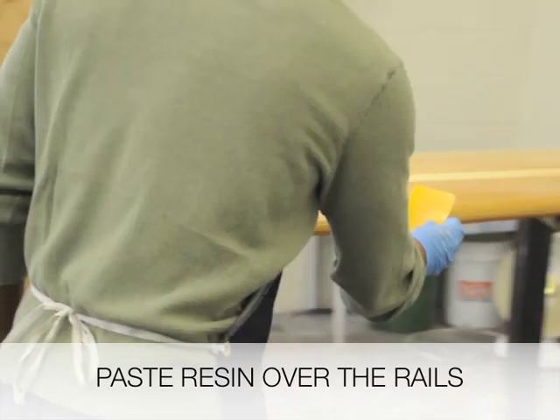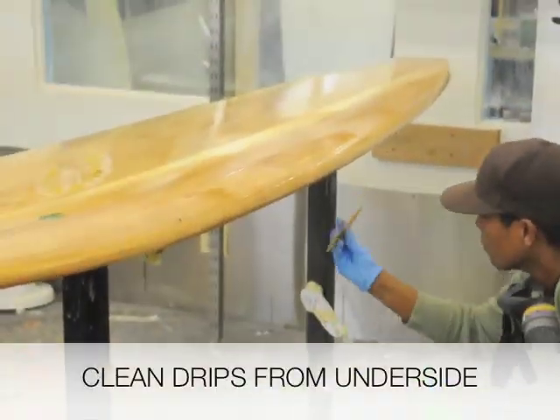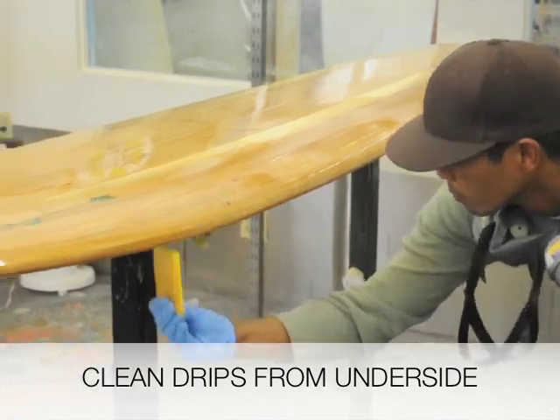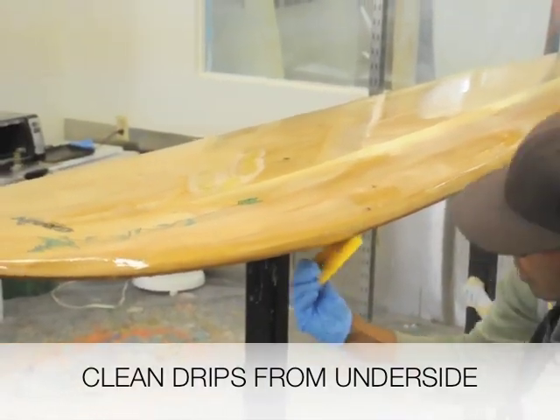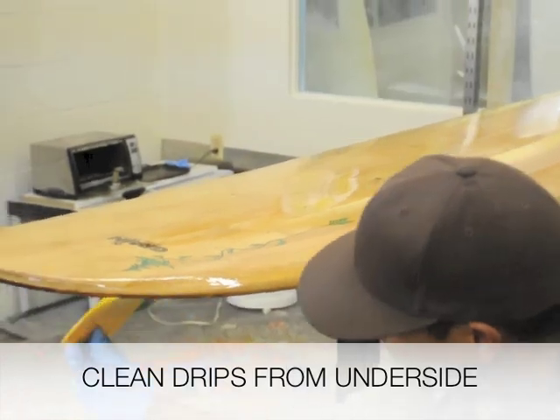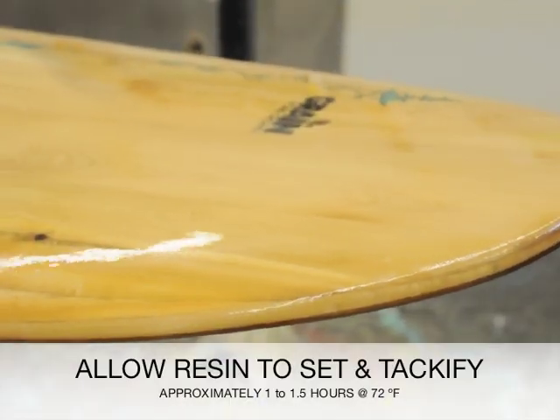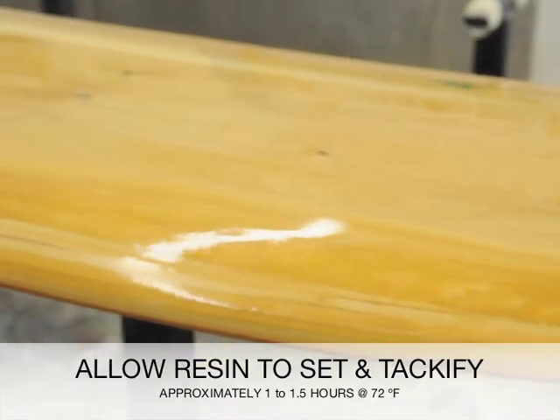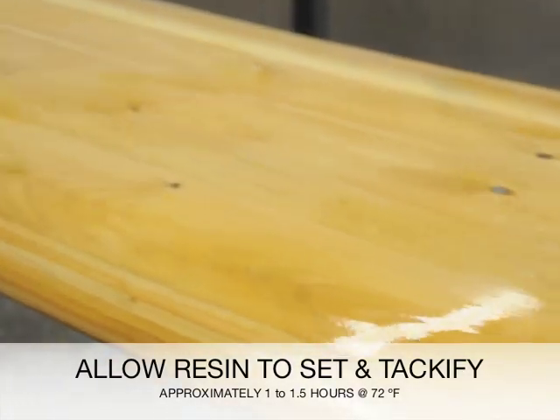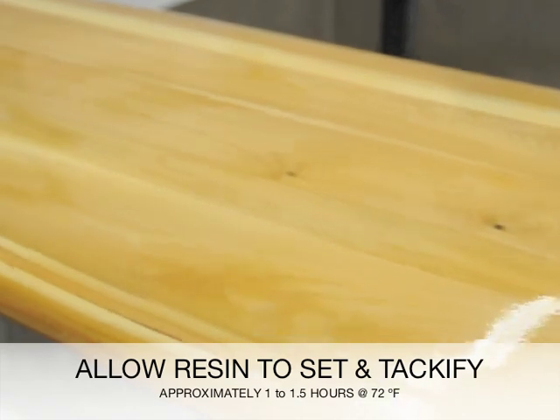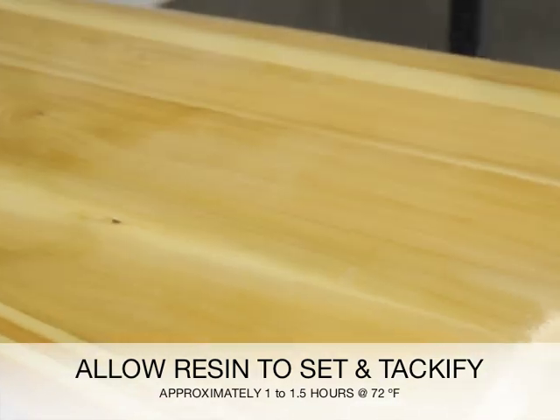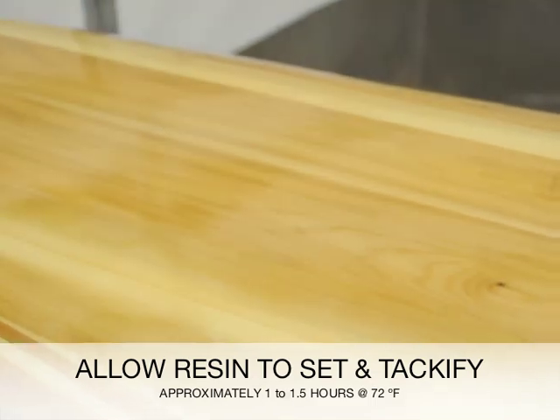Once you have a fairly even layer of resin in the paste coat, be sure to come back and remove any drips from the bottom side of the rail and the board. Finally, wait for the paste coat to set up or go tacky before applying the next brush coat. For the CLR system with fast hardener, this is typically an hour to an hour and a half after mixing.